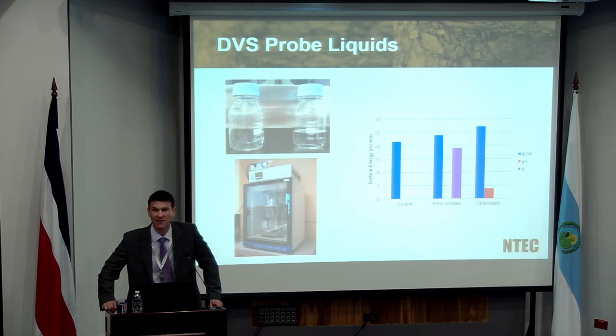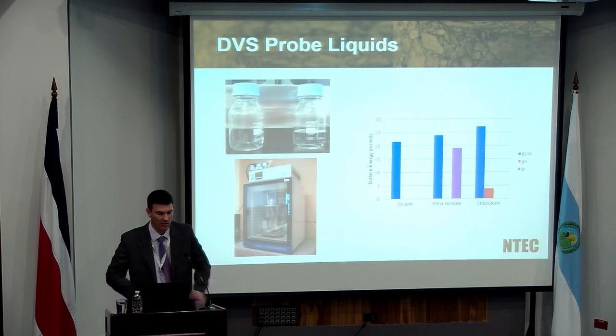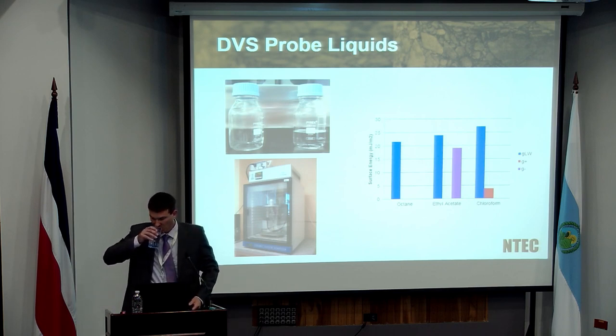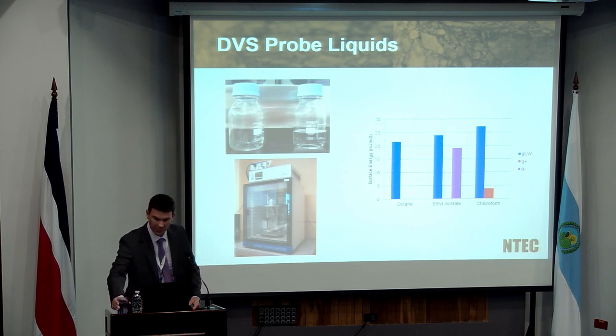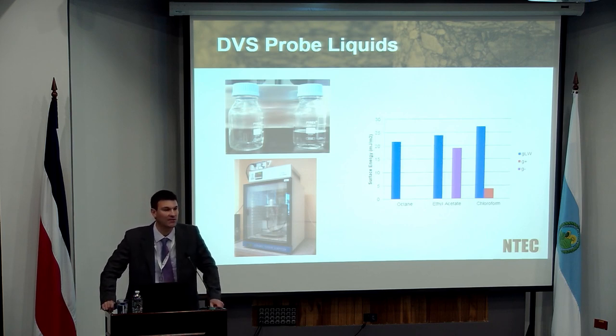And we went through a series of characterizing all the materials used in the UK over a period of about 3-4 years. So taking all the materials that are available or supplied to us by contractors, and subjecting them to the DVS test in terms of working out their surface energy parameters. So that's how we would do it for the aggregate.